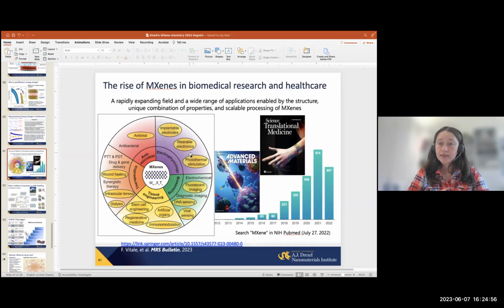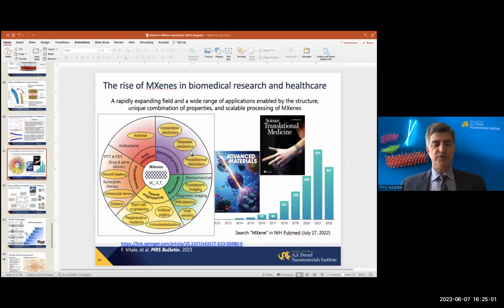We particularly did not, but many of my collaborators, actually visiting scientists also, as my group did. And I think there is strong agreement that at least titanium carbide Ti3C2, niobium, tantalum and vanadium MXenes show no cytotoxicity. There are multiple groups. Some of the leaders are probably Agnieszka Jastrzebska at Warsaw University of Technology. She has published multiple papers. But actually in Ukraine, Professor Maxim Pogorelov and his group at Sumy State University. Maxim is now working in Riga himself, but his group is very active at Sumy State University.